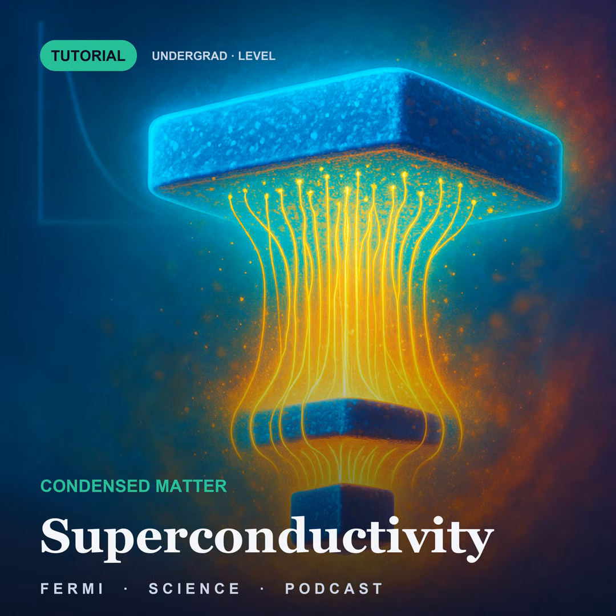What is the second? That the coupling ought to cancel out of some ratio. If the gap is a phonon energy times an exponential, and the transition temperature is a phonon energy times almost the same exponential, their ratio contains neither. It should be a pure number, the same for every superconductor, whatever it is made of. A pure number, and the theory says twice the gap is about 3.5 times the transition temperature in energy units.